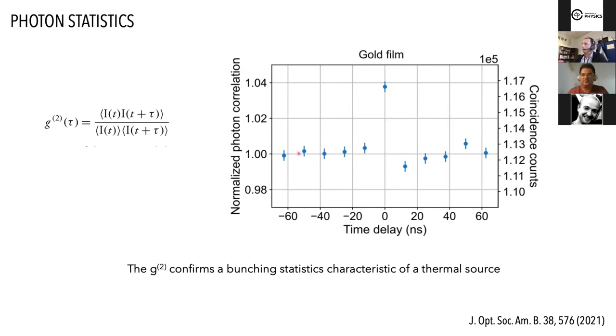It was a hard experiment to do, because we have to make sure that we have enough photon counts to cut down the integration to a few hours, but yet stay below the damage threshold. So Constantin spent a lot of time trying to extract this g2 measurement, but you can see that there is a clear peak above one in this second order correlation function for the photon statistics, which is basically the telltale signature of photon bunching.